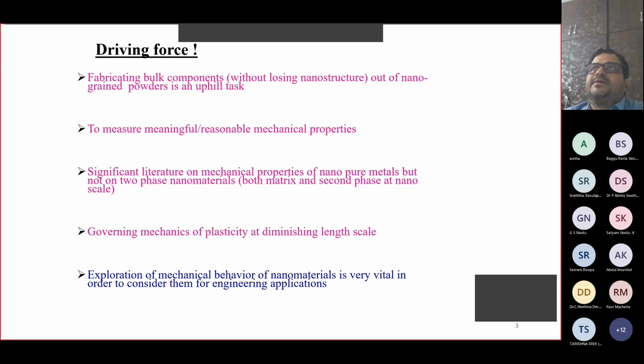In other words, when you work with different polycrystalline materials of structural engineering importance, be it aluminum alloys, copper alloys, steels, nickel-based superalloys, or magnesium alloys, the grain size plays a major role in dictating their mechanical behavior. As a result, if you can control the grain size to less than 100 nanometers, then you can call it a nanostructured material or nanocrystalline material. Likewise, we want to make reasonably larger samples so that the mechanical properties can be evaluated in a more meaningful fashion.